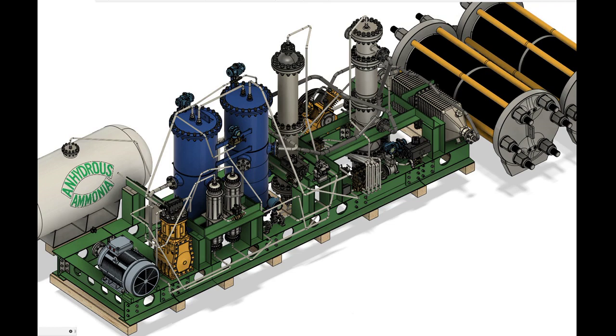The beauty of electrolysis-based hydrogen production is that only one impurity is required for removal: oxygen. While oxygen is still a severe catalyst poison, it is classified as only a temporary poison, since it can be reduced by passing hydrogen through the catalyst bed. One must remember that all ammonia catalysts start off as an oxide of iron, which then undergoes a reduction process using hydrogen. During reduction, water vapor must be kept to a minimum to attain the proper crystal structure. Additionally, oxygen is highly electronegative and has an affinity for virtually every element, allowing straightforward capture and removal using iron particles, for example.